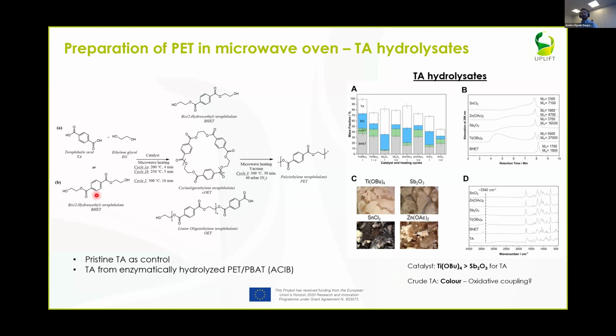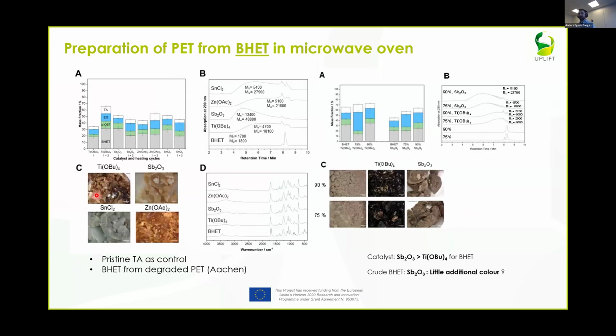If we then, on the other hand, look at the bottom part here, this is one of the other monomers that were achieved from the earlier work packages, where instead of acid, this is work done at Aachen, where they have hydrolyzed the PET and produced BHET as a monomer for further polymerization into PET. So we have done exactly the same study under the same target, in trying to find a good intermediate that we can use for further purification. And if we look at the BHET data instead, we can similarly screen across different choices of catalysts. We can also see that that has different impact in terms of coloration.